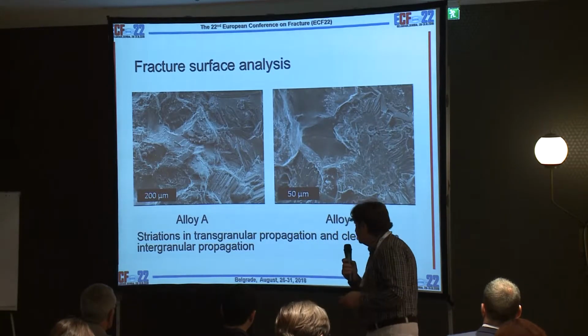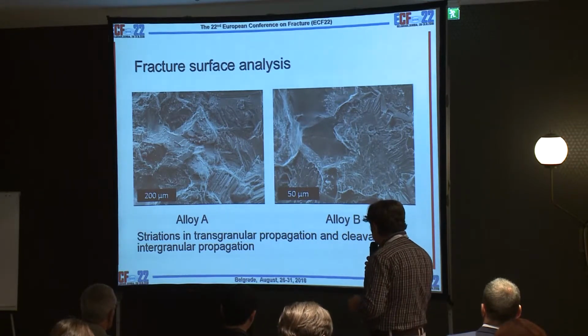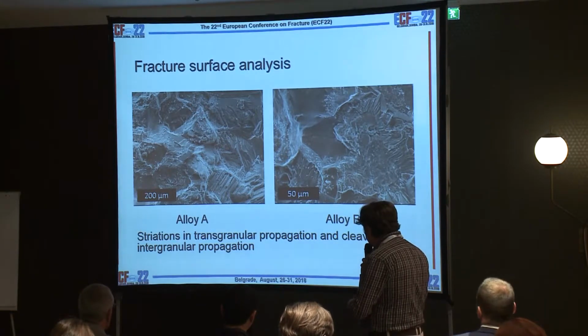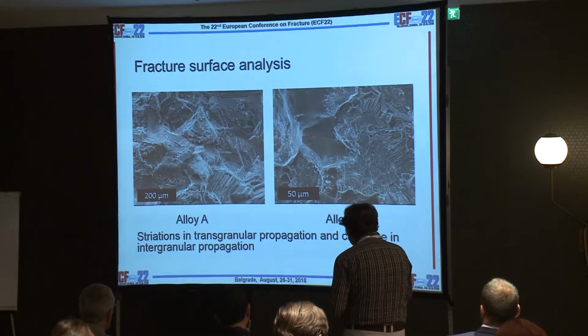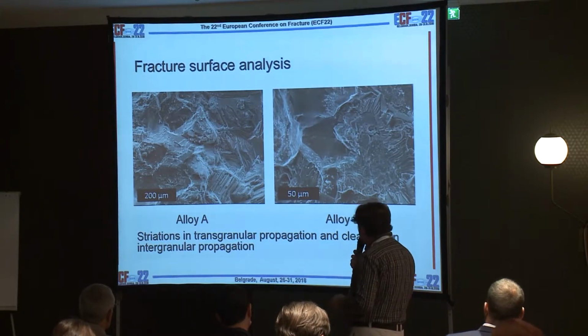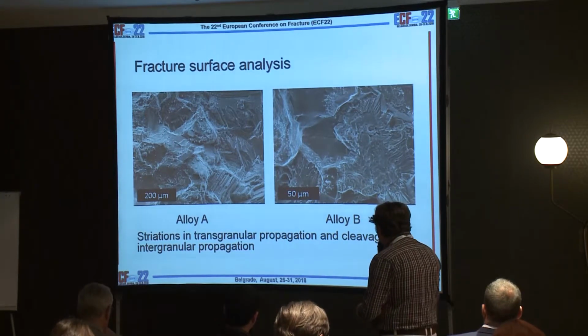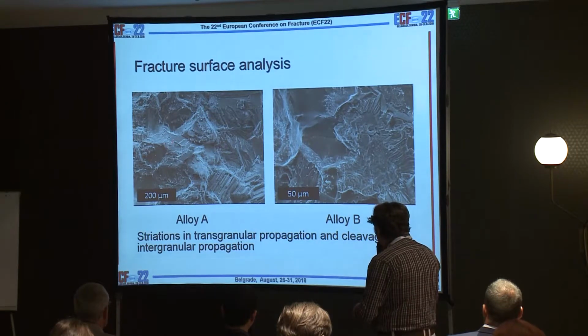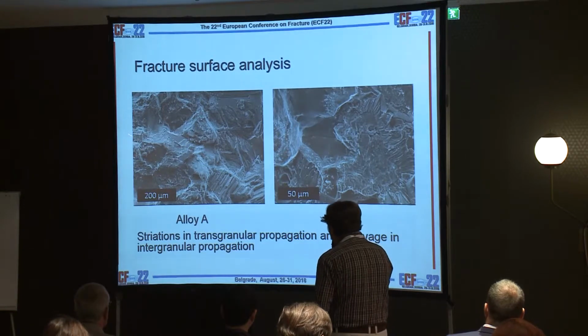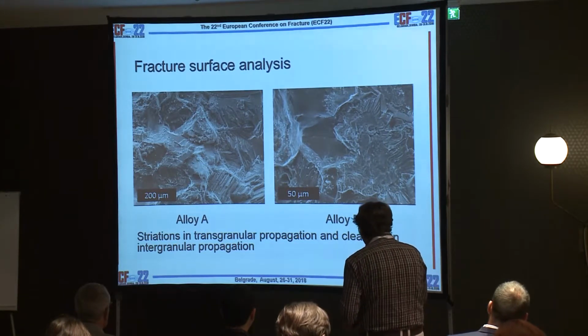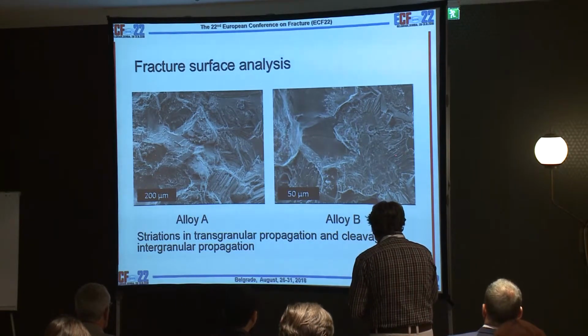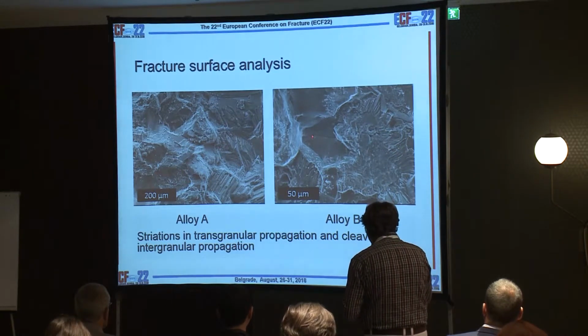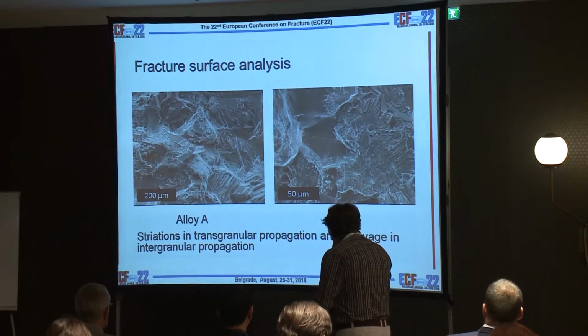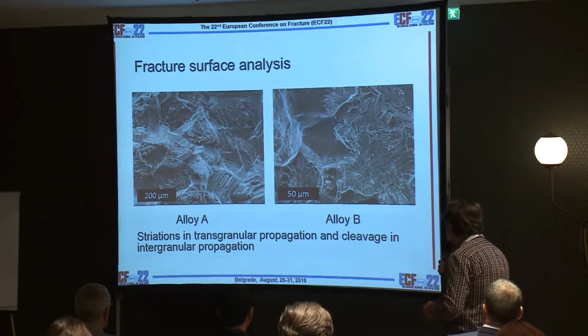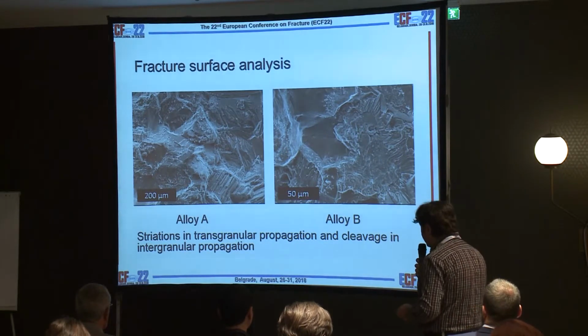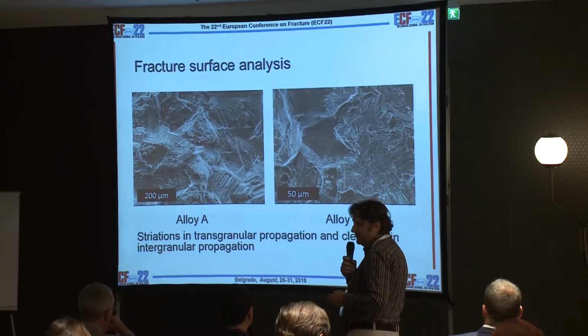In terms of fracture surface micromechanisms, we can see in alloy A the presence of 2 different fracture micromechanisms. In the first one, we have the presence of striation, ductile striation in transgranular propagation. And here we can see the cleavage, often observed in intergranular propagation. In alloy B, you can see a different scale of the grain. We can see the same fracture propagation micromechanism. This is the striation. Here we can see the cleavage, which characterizes the fracture propagation in an intergranular manner. So from this point of view, stage 2 of the two alloys is very close.